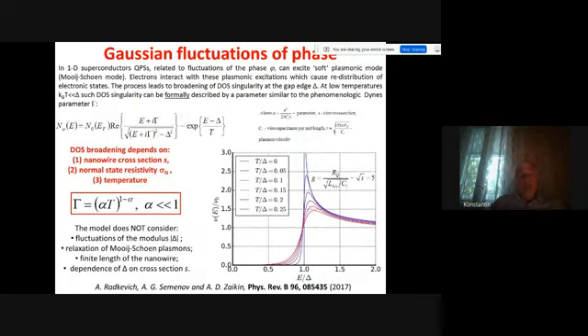And our theorists were capable to show that when the Gaussian fluctuations of the phase happen, it renormalizes the electronic states, which leads to initiation of plasmons, or charge density waves, which propagate along superconducting wire. They're called Mooij-Schön mode. And then they renormalize the superconducting density of states. The plot shows how the density of states is renormalized as function of temperature. At zero temperature, it is classical BCS density of states. But when the temperature is non-zero, but still can be very, very small, much smaller than superconducting energy gap, we have superconducting states inside the gap. So formally, it can be attributed to broadening of the density of states, which is typically described by phenomenological Dynes parameter gamma.